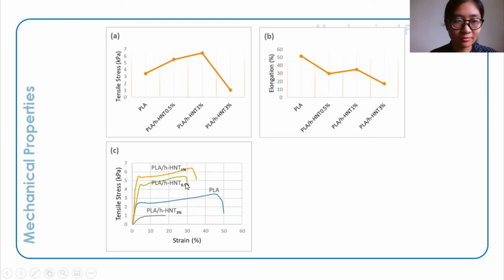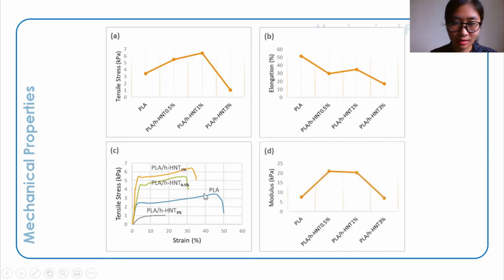So far, 0.5% and 1% h-HNT content has the highest modulus. And then at 3% h-HNT content, the electrospun fiber mat has low tensile strength and modulus. Also shown here, this may be due to the formation of clay agglomerates being a source of weak points resulting in reduced mechanical performance, as observed in other papers.